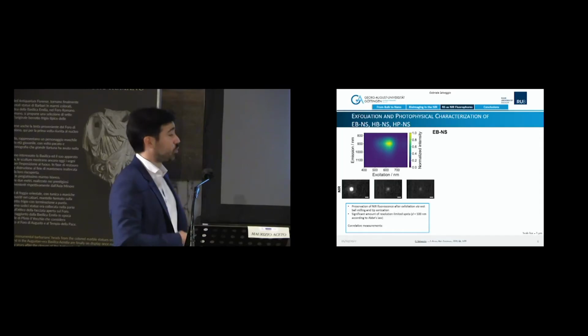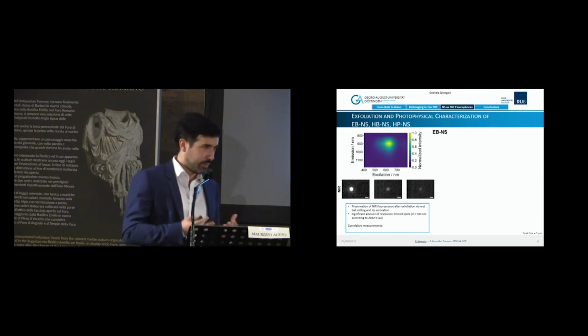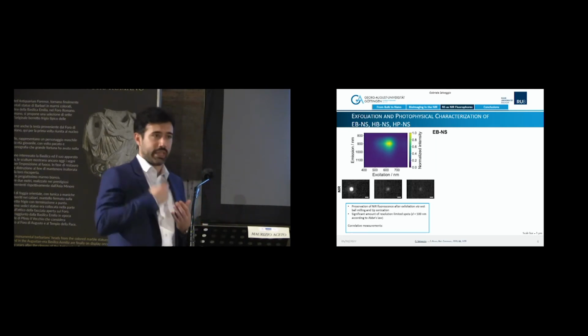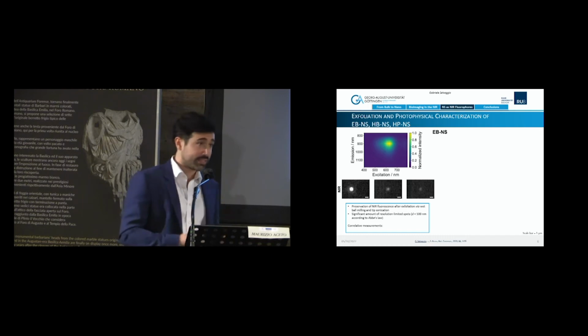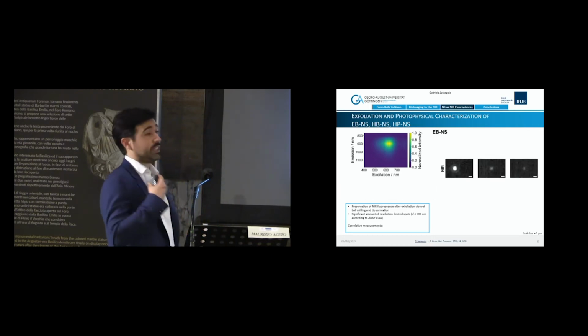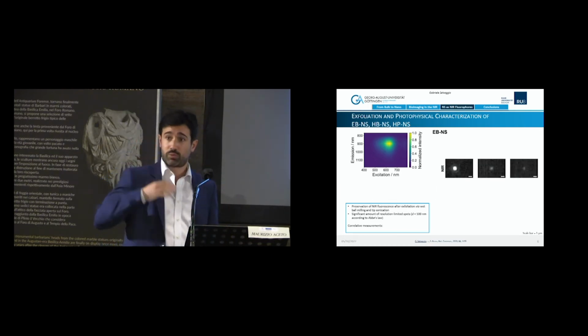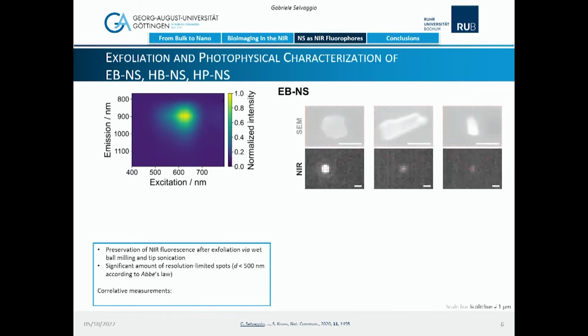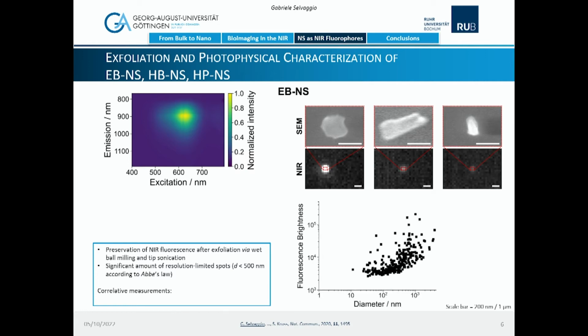So what I did to try to bypass this physical limitation and understand how small we can get without giving up on the fluorescence, I performed correlative measurements, and I followed two different approaches. One was a direct approach, which basically consisted in imaging the same nanosheets in two different microscopes, our near-infrared microscope and also a scanning electron microscope, and also an indirect approach, which is based on particle tracking of the fluorescence of the nanosheets in viscous medium.